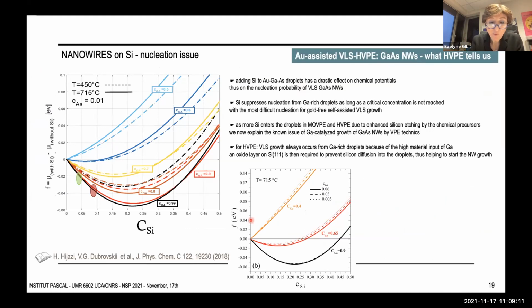So for that, let's go back to gold-assisted VLS to get a high density of nanowires. So nucleation is easier, or seems to be easier, with droplets containing gold. We have shown that there are silicon atoms in the catalyst droplet coming from the substrate. And of course, there is more silicon when growth is carried out on cleaned substrates rather than substrates with their native oxide or partially masked substrates.